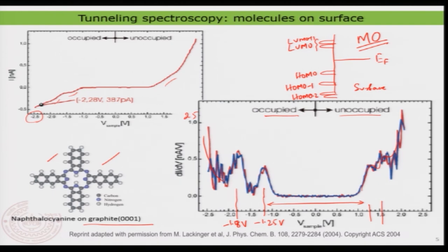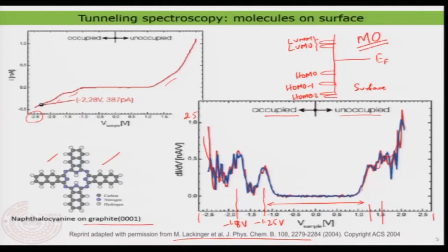This is quite spectacular — we have done it on a single molecule. Please read more details in this paper. We can measure the electronic structure of a single molecule in greater detail. Typically we measure electronic structure from the Fermi level to about ±3 eV and not much more, because beyond that there are difficulties in tunneling spectroscopy due to effects like field emission. Nonetheless, this is the most important region for understanding the valence band and conduction band electronic structure.